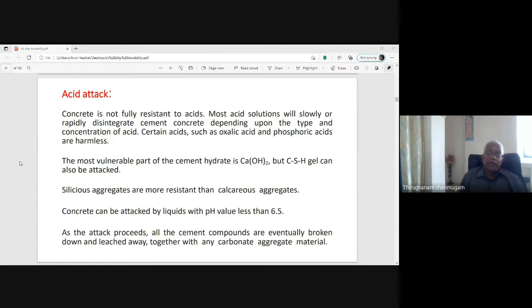The most vulnerable part of the cement hydrate is calcium hydroxide, but calcium silicate hydrate gel can also be attacked. The excess calcium hydroxide liberated from the hydration process is easily attacked by these acid solutions, and it causes the disintegration of the concrete cement paste. Siliceous aggregates are more resistant than calcareous aggregates. That is one of the prime considerations in selecting the coarse aggregates. In aggressive environments exposed to acid attack, you have to select only the siliceous aggregates, not the calcareous aggregates.